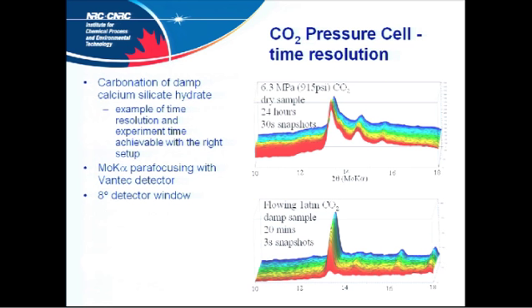Again, this is moly, because we had to get through the windows and the CO2 and everything else. 8-degree detector window. And here, we actually made the sample damp. And this is where you actually get a slight problem, because you've got water in there as well. So you start getting meniscus and a few other nasty things. So you've got a little bit of water to try and get through.